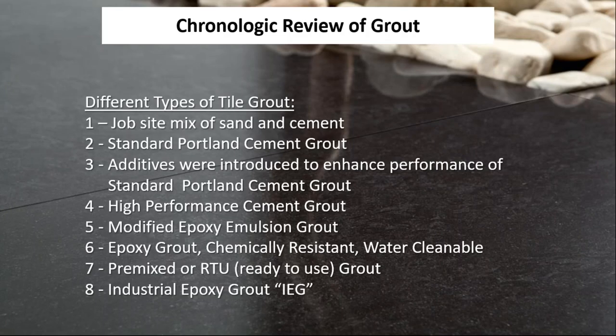So different types of grout we're going to talk about. Job site mix of sand and cement, standard Portland cement grout. We added additives to enhance the performance of the standard Portland cement grout, which made it denser, made it stronger, just a better all-around performance of a standard cement grout. Then you get into a high-performance cement grout, calcium aluminate. So it's not Portland cement based. We're going to talk about a lot of the advantages in using a calcium aluminate grout, high hydrated cement versus a Portland cement grout. A modified emulsion, an epoxy, a chemically resistant epoxy.